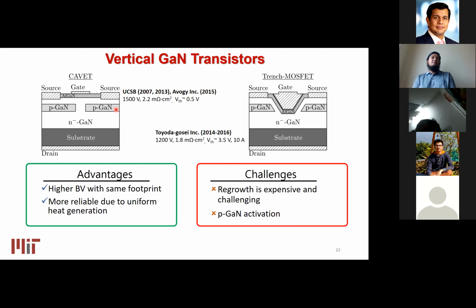The second problem, which is fundamental to this gallium nitride technology, is the P-type doping. Unlike silicon, gallium nitride doesn't have an efficient P-type doping mechanism. So getting a desired P-type doping in gallium nitride is very challenging, and that's very inefficient. So if you want to make a technology in gallium nitride successful, it most likely has to be a structure that doesn't have a P-type region or regrowth.